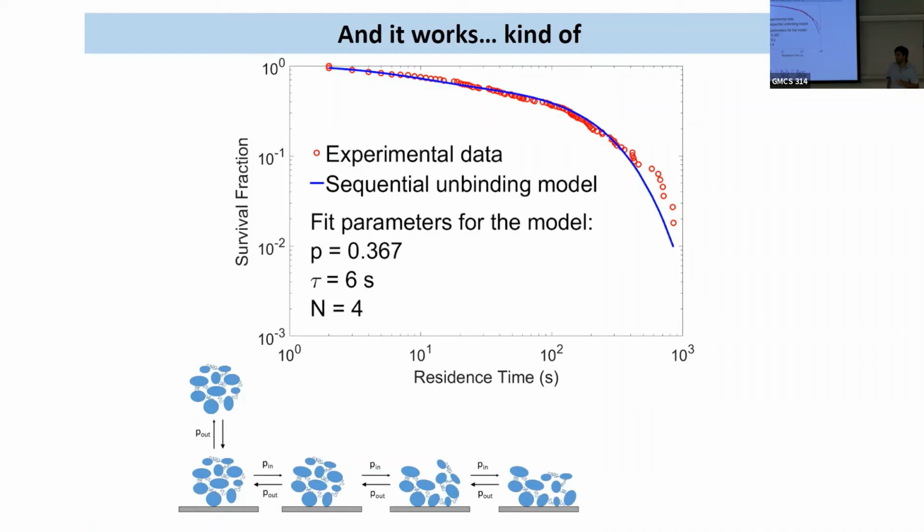It doesn't have to be. So I'm assuming there's a P in and a P out, but as long as there is a common average P in and a P out and they don't vary too much, I'll still get a similar output. I'll show that. The potential explanation is that for every conformation change, you're probably breaking a similar number of hydrogen bonds or whatever, and you're unfolding. So the energies can be different, but not too different.